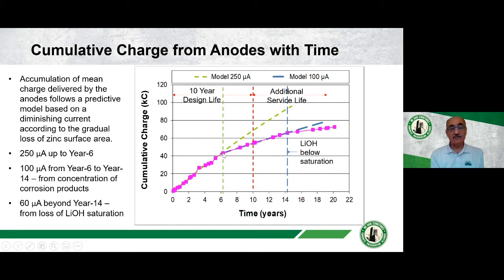So for the first 6 years, we were seeing that actually it was bang on. The assumed current density that should have been delivered by the anode was actually being delivered. We then had a little bit of a diversion from that line, but then it followed a second line consistent with a 100 micro current density, current output. And then there was a third deviation, or rather a second deviation, where the current output diminished to something like 60 micro. Obviously, something would have caused these to happen.